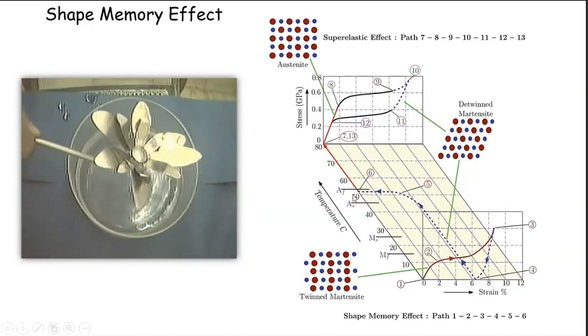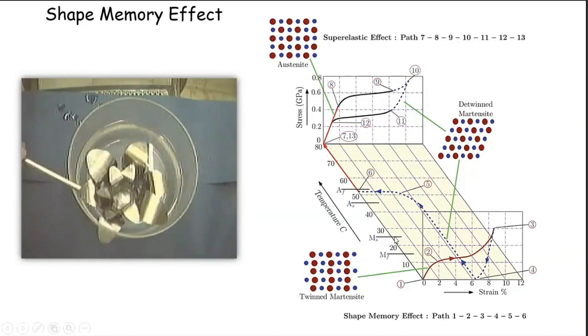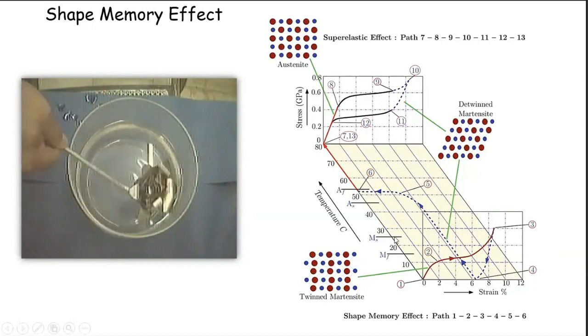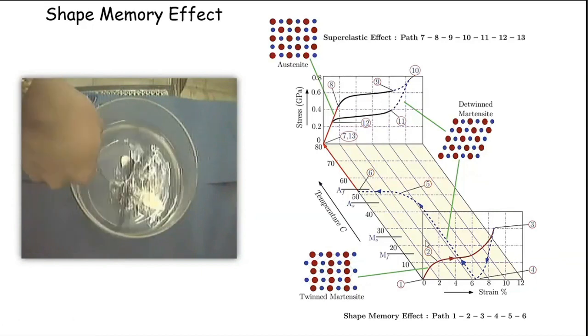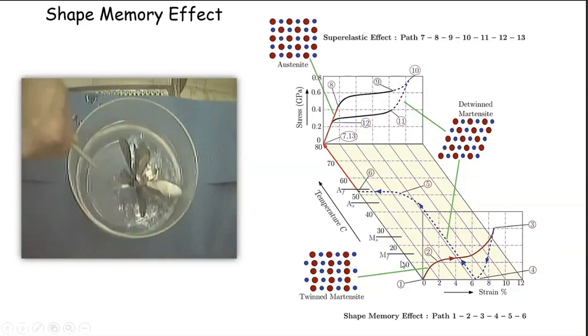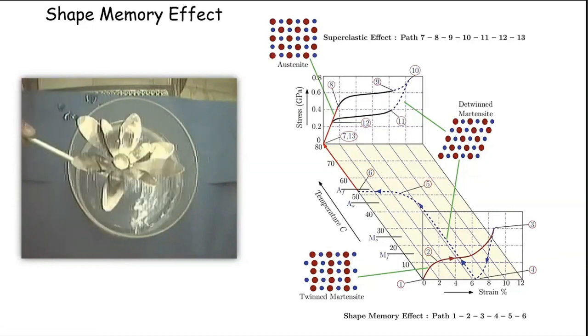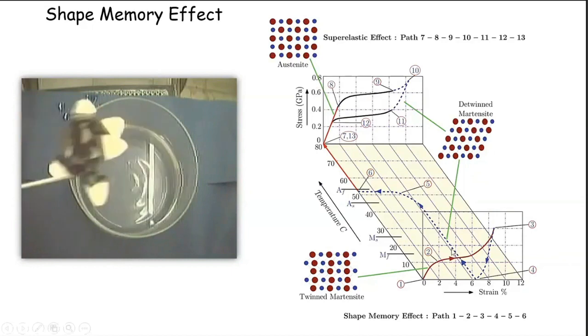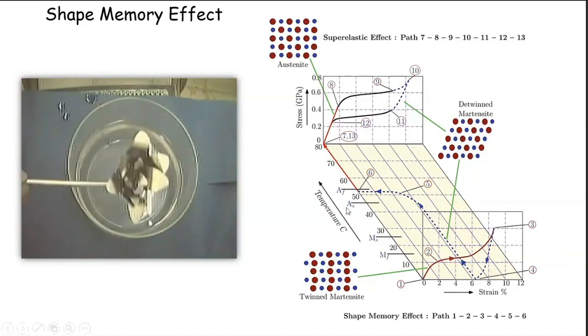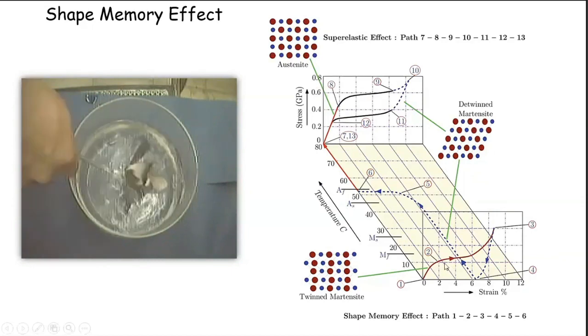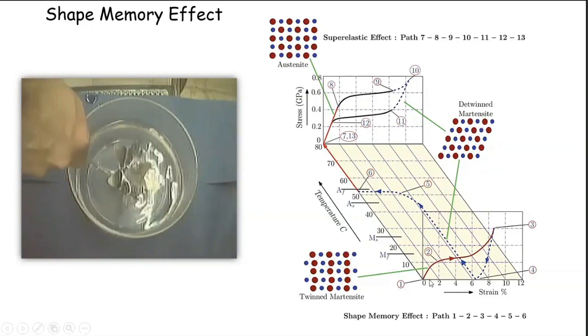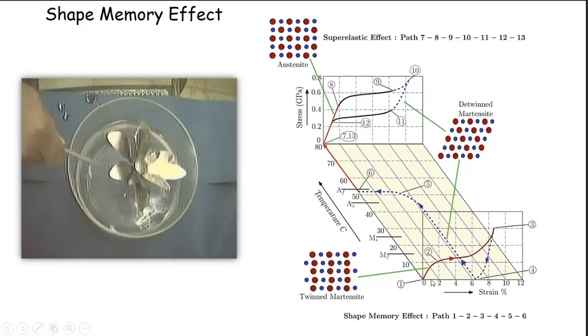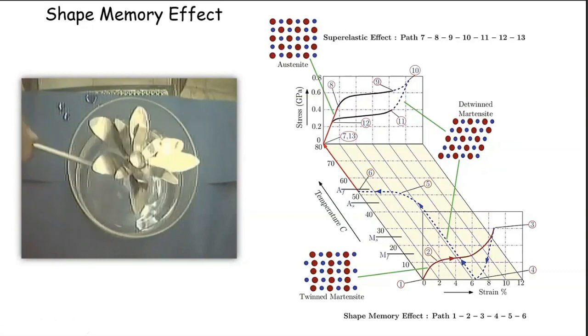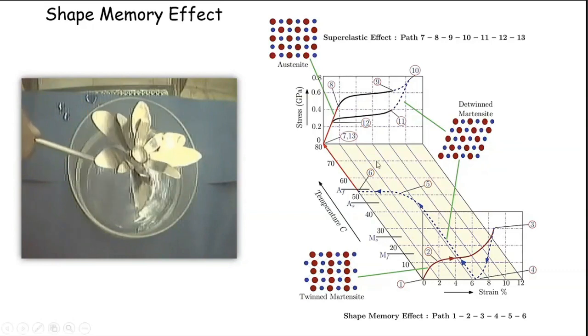And you cool it, and at a temperature MS, it starts softening, or it starts acquiring this property of becoming soft, and then by about MF, it is back into its very soft and pliable state where you can deform it again, and you can cycle this whole thing, and when you heat it, it once again recovers. So the state when it is at room temperature, as is shown in this case, is its martensitic condition. And when we heat it, we'll refer to this as the austenitic condition, where it has recovered its original shape.